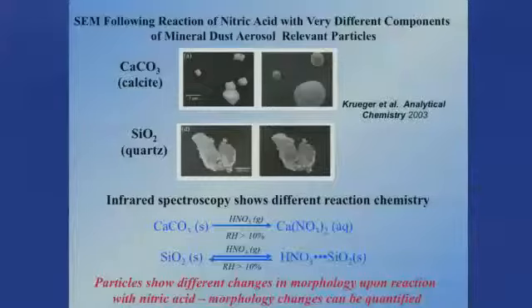Okay, so we did some work early on, and I'm just going to show you this as an example. Here we were working with Alex Laskin using scanning electron microscopy to simply look at the reaction of gas phase nitric acid with different components of mineral dust particles. And so here we're just zooming in on a picture of calcium carbonate particles, or calcite. Here we're zooming in on a quartz particle, silicon dioxide. And what we did was we exposed these different types of particles to nitric acid vapor at different relative humidities. In the case of the quartz particle, just viewing this, we see very little has happened, as indicated by these two images, before and after reaction. But in the case of the calcium carbonate, we see very significant changes.